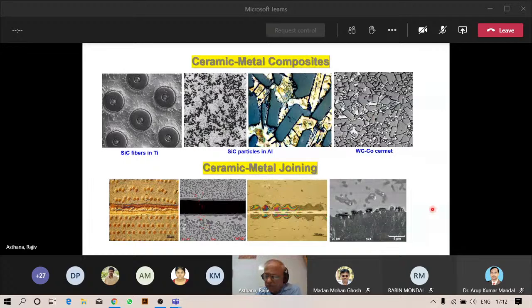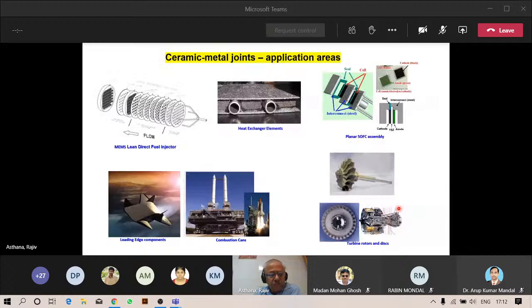So my interest has been mostly in these areas of joining. We looked at joining of Kovar or other low expansion metals and alloys with silicon carbide. The application was for a fuel injector for NASA's micro electromechanical system. So fuel and air are basically mixed like in any standard injector, and the Kovar tubes had to be bonded to silicon carbide discs here. Heat exchanger elements. We were looking at bonding titanium tubes to carbon foam sandwiched with carbon-carbon composite, high conductivity carbon-carbon composite. So the idea was for a fluid to flow through the titanium tube and dissipate heat to high conductivity materials around it.